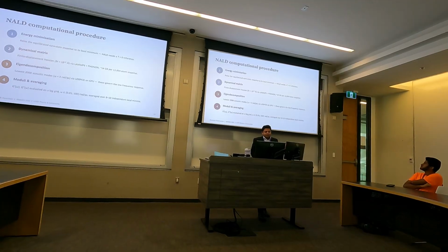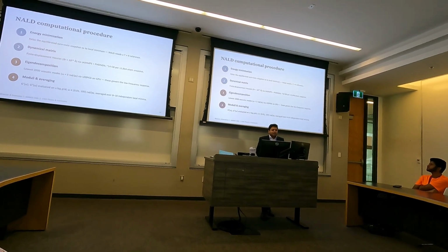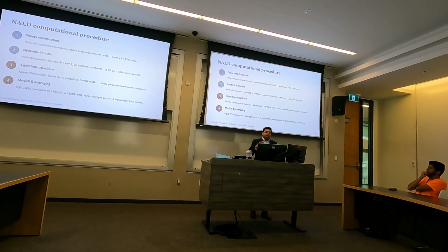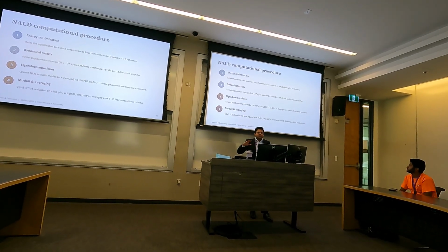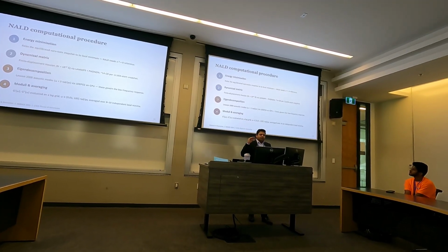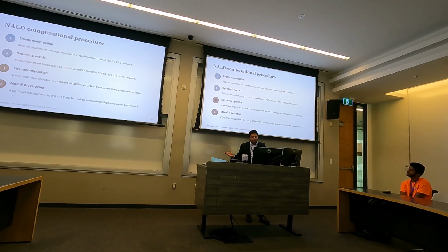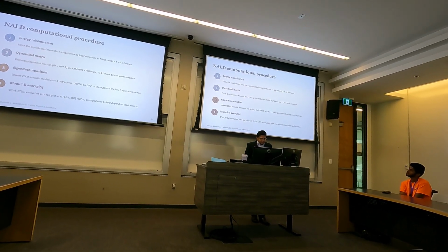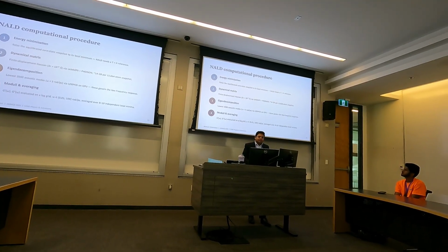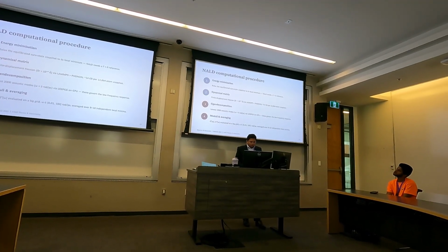So the computational procedure for calculating viscoelasticity using the NALD process is, firstly, we minimize the curing snapshot, because now we have a snapshot from each and every time step that we want. We first minimize the energy, because this is a temperature equals 0 Kelvin reference. Once we have that, we can calculate the dynamical matrix by the finite displacement method, and we are doing this in LAMMPS.